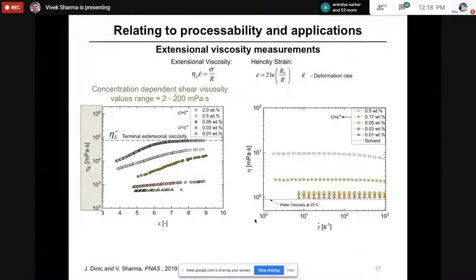What is more interesting, though, is the fact that if we have the radius evolution data, from that we can get capillary stress. We can also calculate extension rate. And by taking the ratio of stress to rate, we get an effective extensional viscosity. I mentioned for dilute solutions, the shear viscosity is less than 2 times water viscosity. So less than 2 times water viscosity is 2 millipascal second. Here, the extensional viscosity that's measured is orders of magnitude higher, right? So we really have this transition from, so here's the shear viscosity values, here are the extensional viscosity values. You're going from around 1 to anywhere between 10,000 to 100,000. Something that behaves like water in shear is behaving like honey in extension.